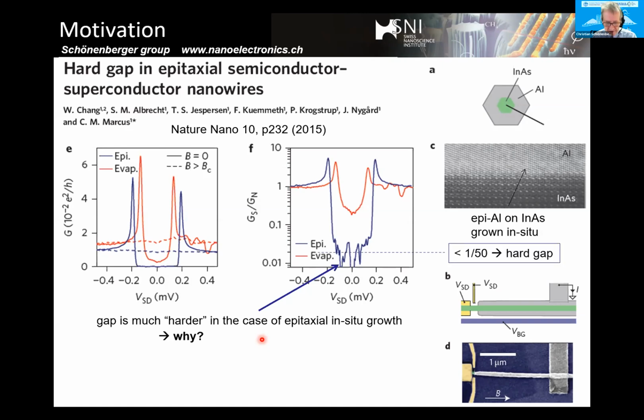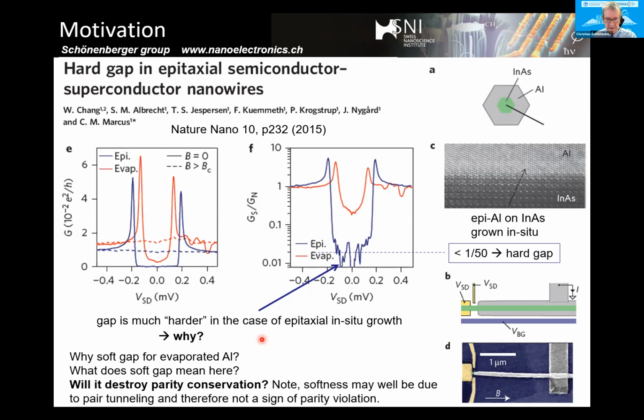So for me, it's still a question why a soft gap appears, what's the origin of the sub-gap, and most importantly, eventually, it's maybe not so important whether the suppression is strong in the superconducting state here. Most important is whether the parity will be conserved. So even if there is a soft gap, if you can prove the parity is still conserved, then it is not really an issue.